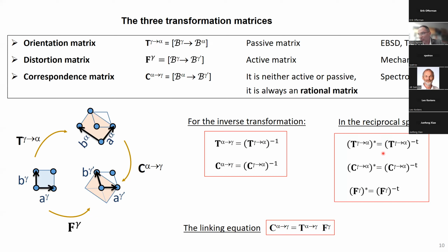And if we need to do some calculations in the reciprocal space, okay, here it means that we work in the reciprocal space. If we want to work with planes instead of directions, we use this matrix with a star here. The star is just the inverse of the transpose of these matrices here. And there is a nice relationship between the three matrices. It's that the correspondence is the orientation relationship matrix multiplied by the distortion matrix. And we will use these equations later.